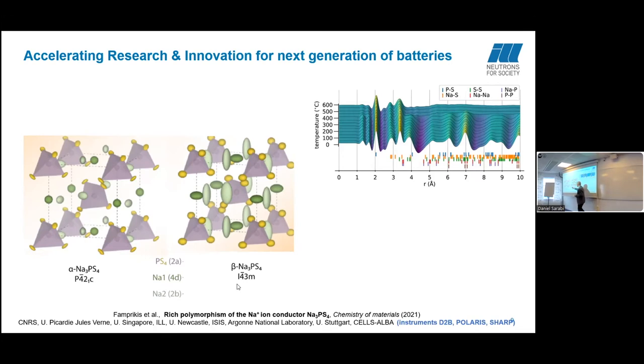And what we actually have is this structure surviving into the beta phase, but with disorder. And furthermore, when you go into the high temperature structure above 500, all of the peaks associated with sodium disappear. So you've effectively got a fluid or a liquid-like sodium structure. The thiophosphate tetrahedrons, they're still there. And so there are tetrahedrons spaced in a cubic structure with a fluid or a liquid of sodium in between, which I think is really interesting.